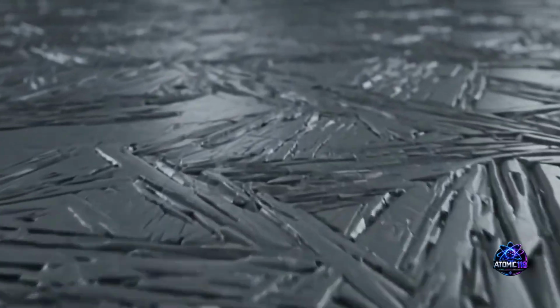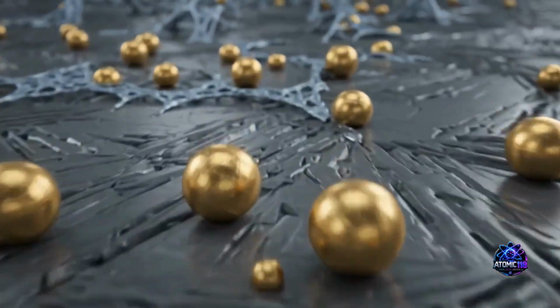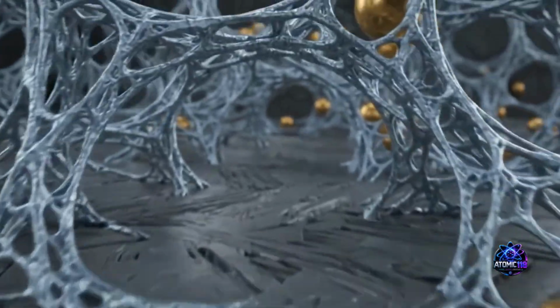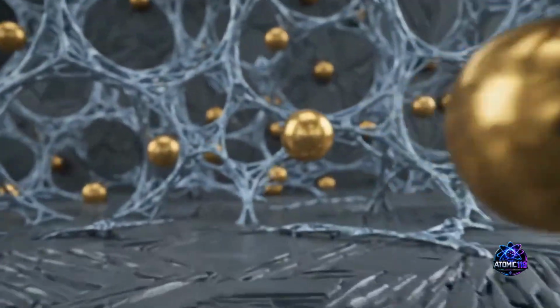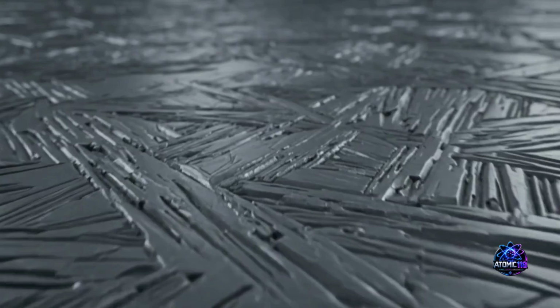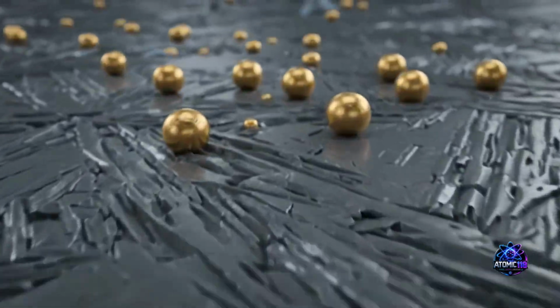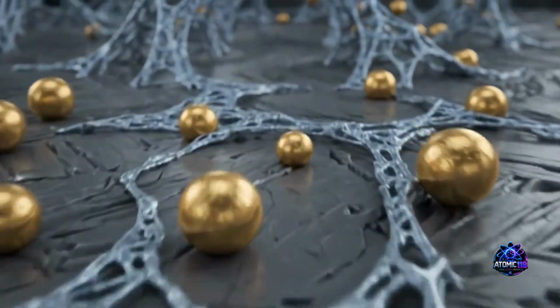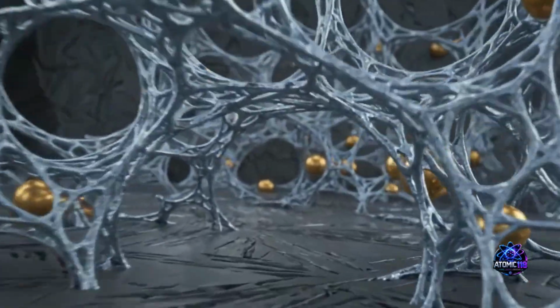They engineered an alloy using 0% tungsten, replacing it with a very specific mix. 7% molybdenum, 7% vanadium, and 2% carbon. A 7-7-2 ratio. How do the two transition metals interact when they are forced into the same carbon matrix like that? They divide and conquer perfectly.